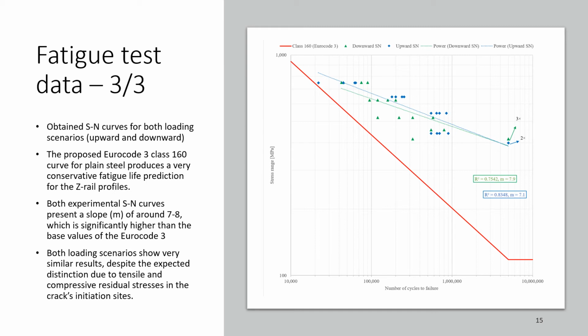You can see here that the class 160 from Eurocode 3 for plain steel produces very conservative fatigue life predictions for these rails. And we can also compare these two lines, and they have very similar results, despite the fact we were predicting some distinction due to the tensile and compressive residual stresses located in the crack initiation sites. Now, one thing to note is that both of these lines have a slope of around 7 to 8, the m value shown in Eurocode 3. These are much higher than the base values of the design code.